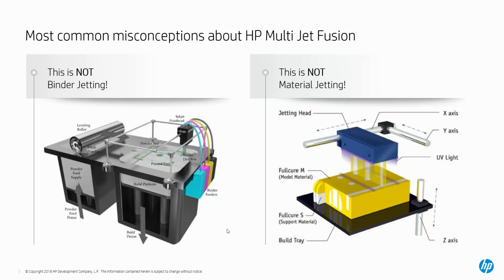On the right-hand side, you have material jetting, which uses UV light in order to cure thermoplastic, essentially acrylic-based materials. So very similar in the process, except you're dispersing the material down onto the bed as opposed to Multi Jet Fusion, where the powder is the bed. So it's a little bit reverse, and the materials are very different in their properties.